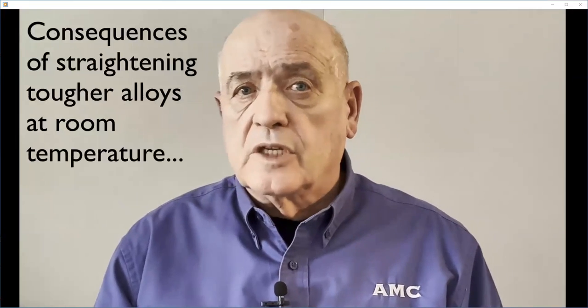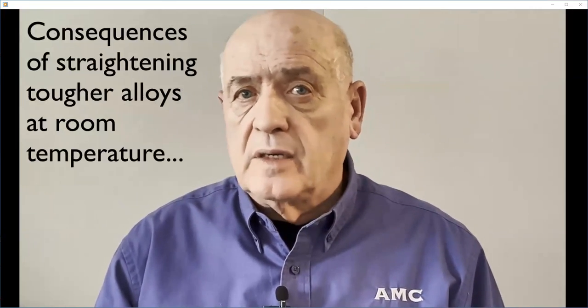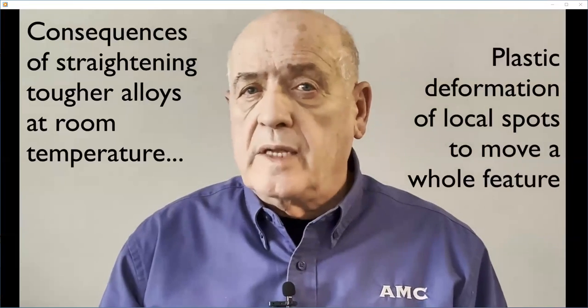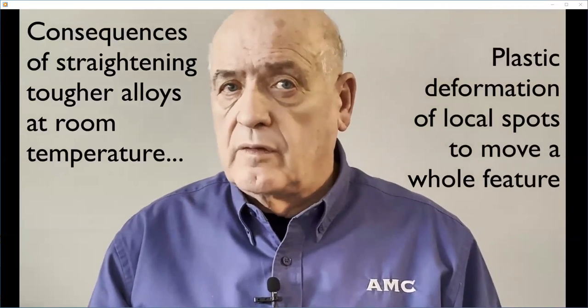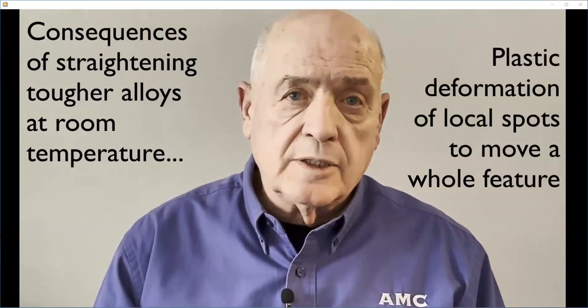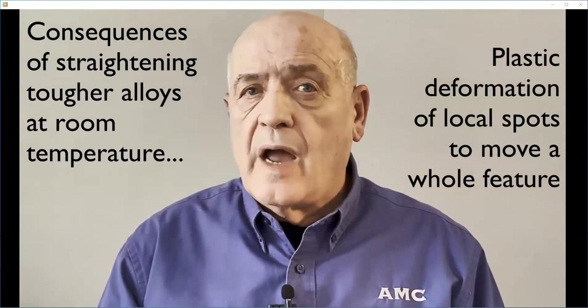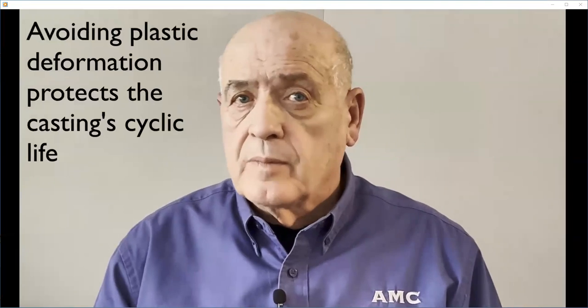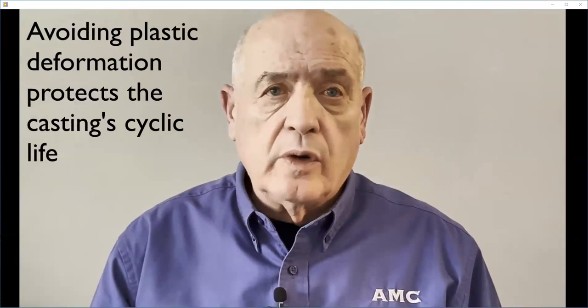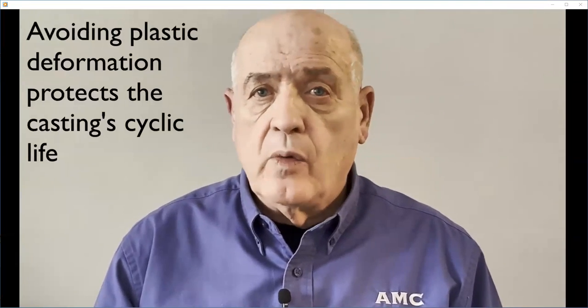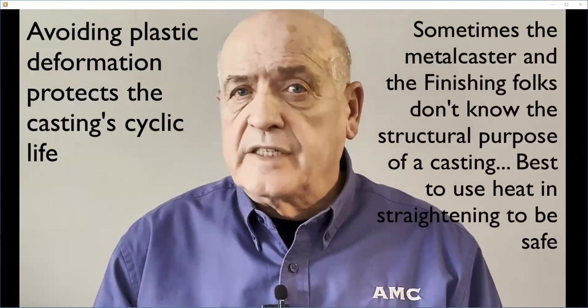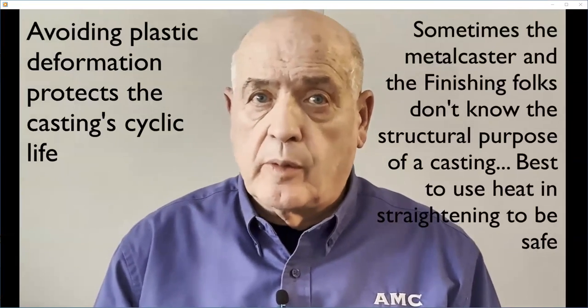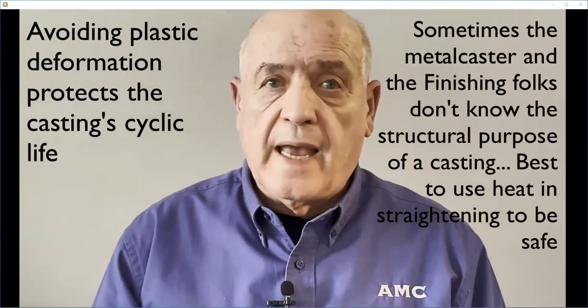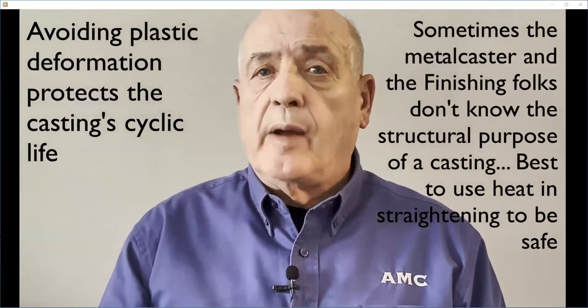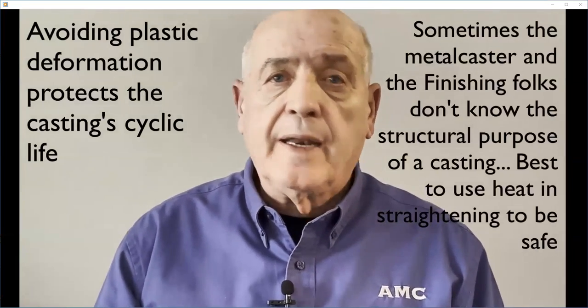Some alloys, especially the steels, can be straightened at room temperature without causing a crack. However, doing so means that the metal is being plastically deformed in local spots to enable movement of an entire bent or twisted feature. Plastic deformation shortens the cyclic life of a metal component. Perhaps the casting only has a static structural purpose or no structural purpose at all, but the finishing folks probably have no idea about any of that.